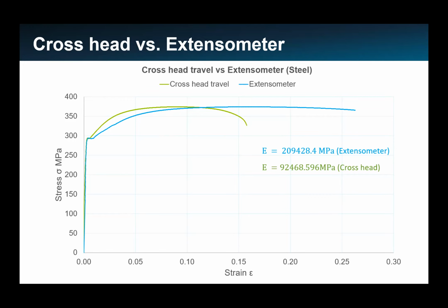As we know, the Young's modulus for steel is around 210 gigapascals, and that's the result we obtain with the blue curve. But if we compute the Young's modulus using the crosshead, we obtain a totally different value. So we need to discard this value.